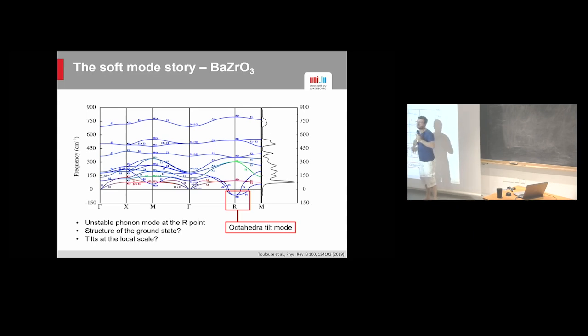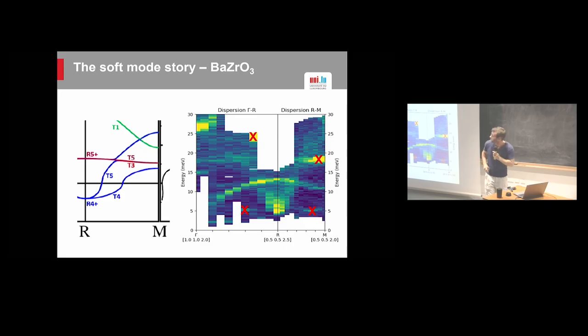So we are not at gamma, so no way to use optical techniques. And for this one, we actually did both. We did X-ray and neutrons. So I'm going to flash a couple of those maps that you can see. So this is an example of phonon dispersions mapped by neutrons. So this is the ILL.